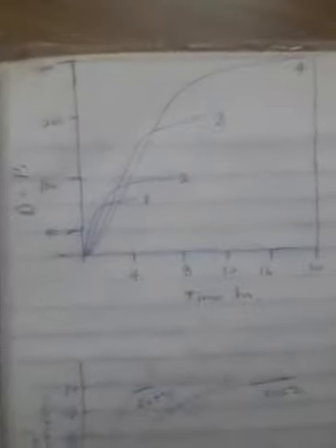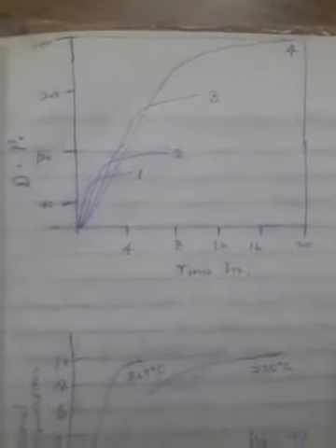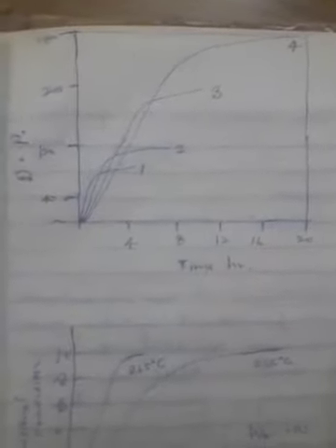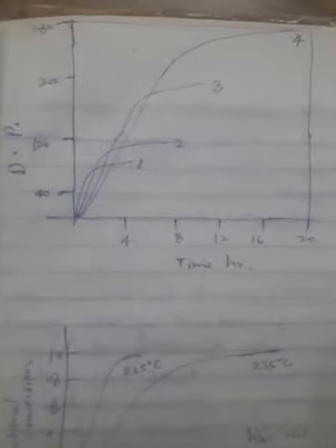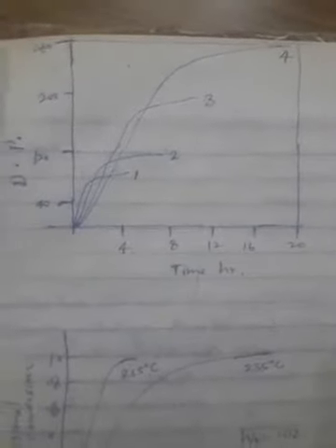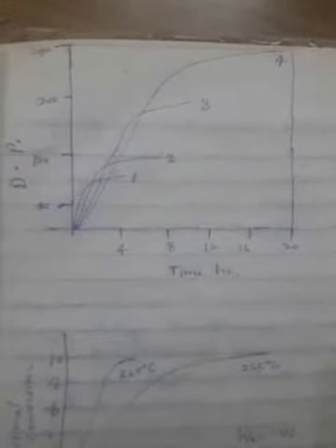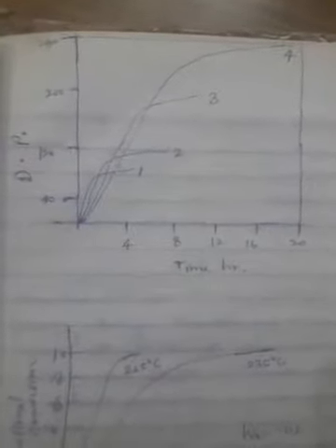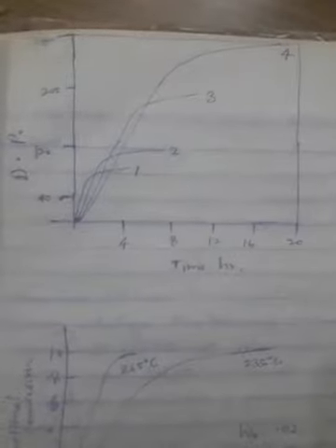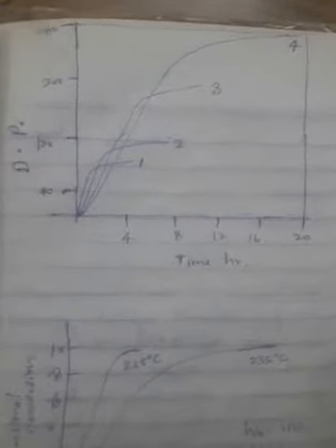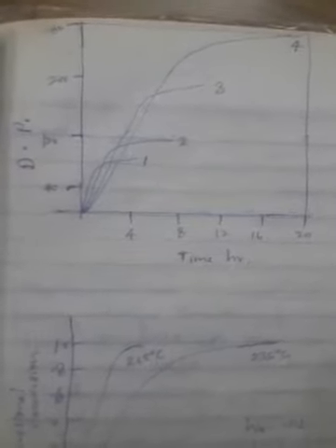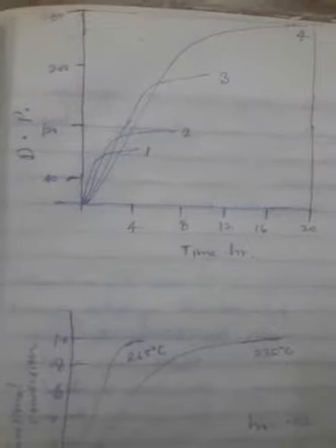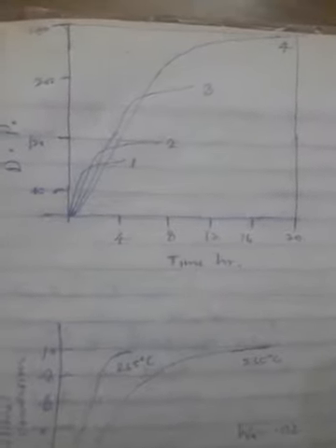And here is another, the effect on yield, that is the degree of polymerization. You can see here, as I already said, the increase in water reduces the final DP of the polymer. Curve 1 means 8% water, 2 means 4% water, 3 means 2% water, and finally the fourth represents the 1% water curve.